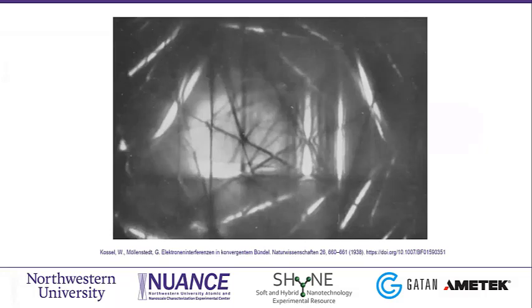So to start, I really like to start my talk with this diffraction pattern here. This is one of the first, if not the first, convergent beam electron diffraction patterns taken. That was back in 1938. And you might recognize some of the names, like Kossel and Möllenstedt. They did this, if I remember correctly, on a mica sample, and it was done at 45 kilovolts.